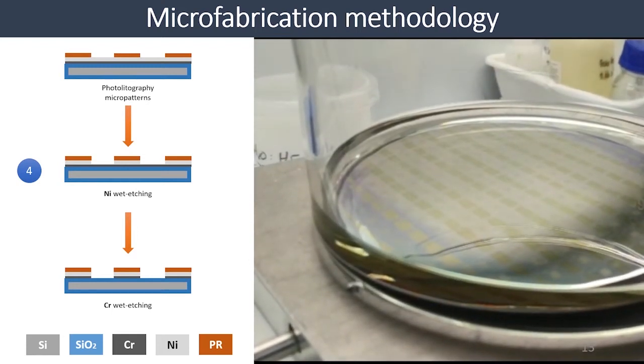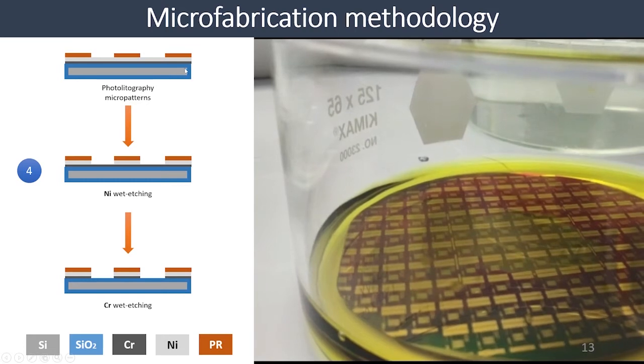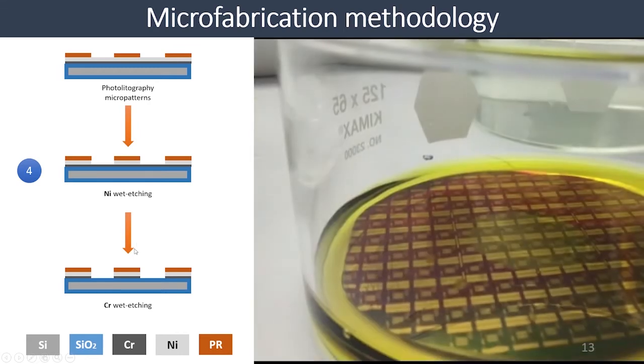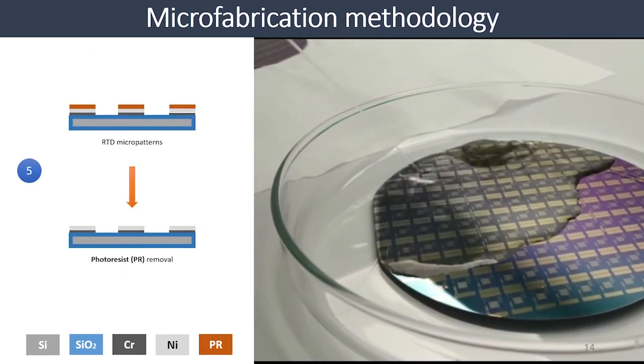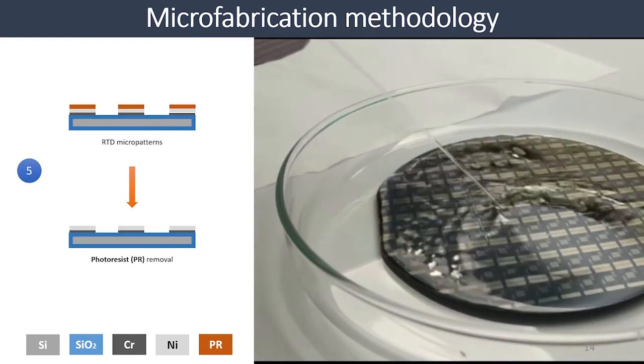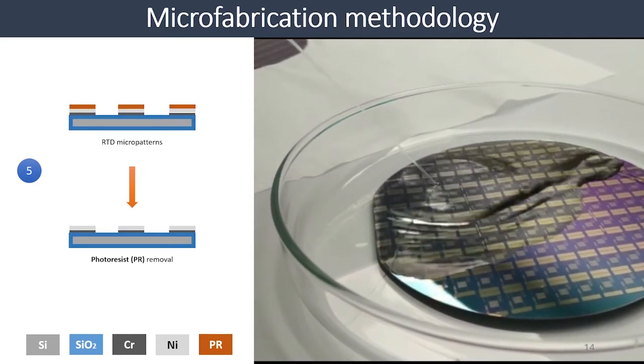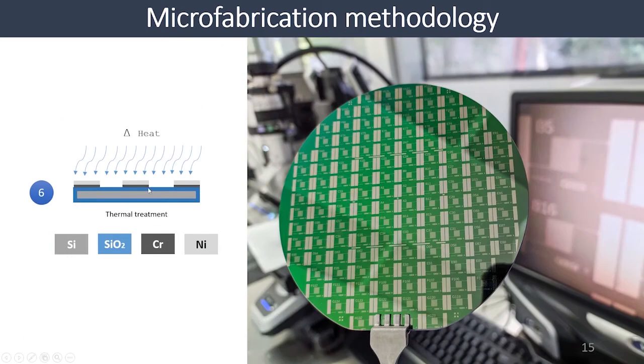Then we proceed with the metal definition, starting with the previous photolithography micropatterns. We etch the first exposed metal, that is nickel, and then we expose also the second metal, that is chrome, both with their specific etchants. Then finally we have our sensor, so we just proceed to the photoresist removal and cleaning of the wafer. And finally, the last step is thermal treatment. The reason for this is to increase the crystallinity of nickel and homogenize all the RTDs in the wafer. Also to prepare the material for the next soldering processes to which all the RTDs will be subjected. The thermal treatment consists of 20 minutes at 300 degrees Celsius in a nitrogen-rich environment.